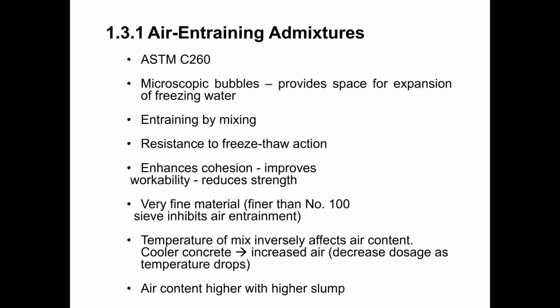All right, there's also a relationship between air content and slump. Generally, as air content goes up, we're going to get a little bit more workability as well. So if you're a little bit low on your slump, but you're also low on your level of air entrainment, then you may want to try adjusting your air content to get it into the range where you want it, and then reevaluate your slump, because just by increasing the air content, you may get an additional amount of workability that meets your requirement without having to actually increase your water cement ratio or the amount of water reducer that you're using.